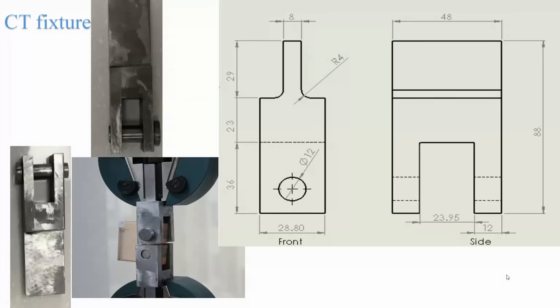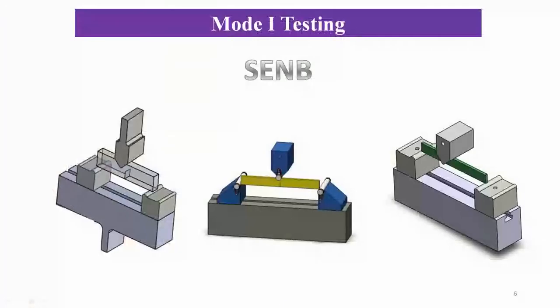Over here you see the drawing of the CT fixture. Dimensions are assigned to make sure that they fit properly in our universal testing machine that will be introduced in the next slides. Over here you see what has been manufactured and used in our lab. There was a minor modification to fit the part properly in the UTM grip, and this is the whole set of CT parts used in the CT testing, while the specimen is fit into the upper and lower yoke of the CT fixture.